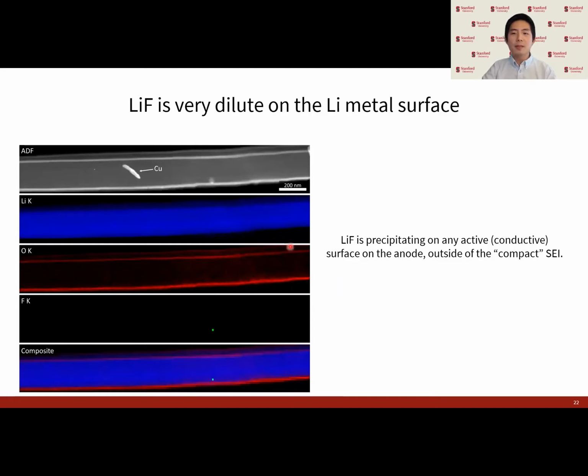So based on these previous observations on that model substrate, we can start to see that these lithium fluoride particles are actually quite dilute. Once you plate out lithium metal, you increase the surface area of your electrode dramatically. If we map enough of these lithium metal filaments, which are much higher in surface area, we can then see these dilute lithium fluoride particles. And based on the dilute nature of these particles, where there are only single particles across microns of length of lithium, we can start to see that these lithium fluoride particles likely contribute very insignificantly to ion transport across the electrode.